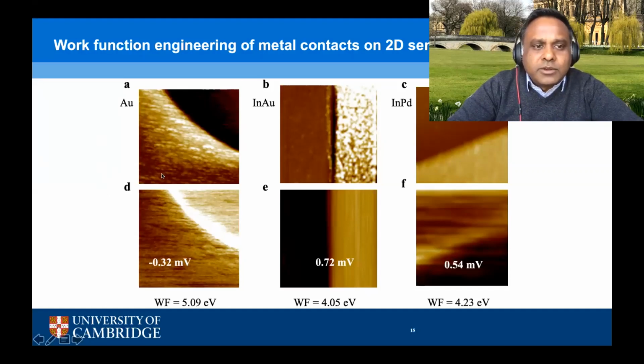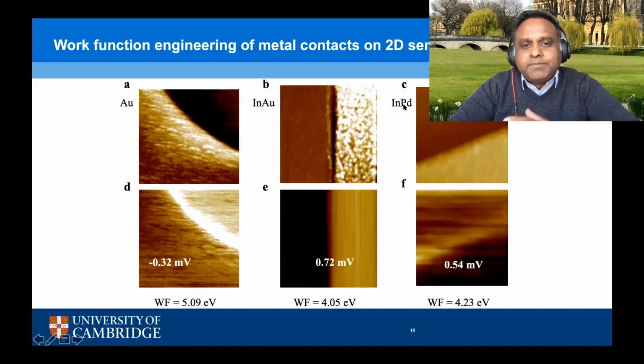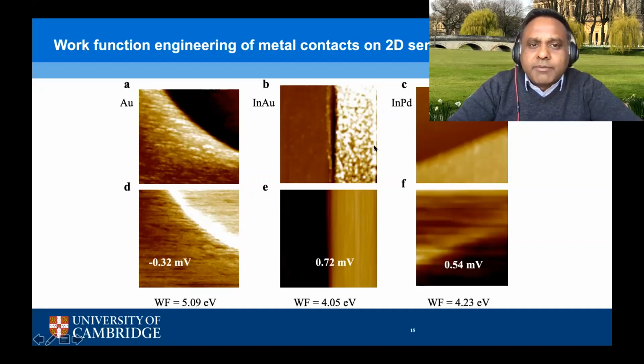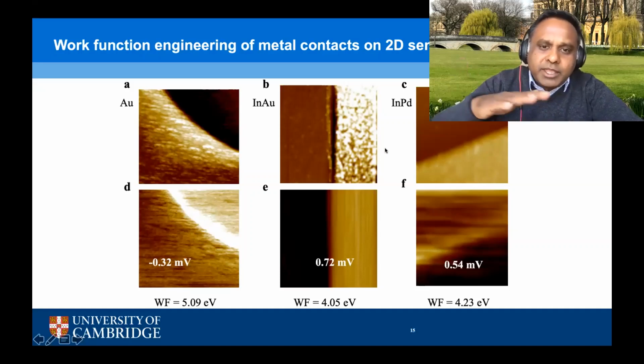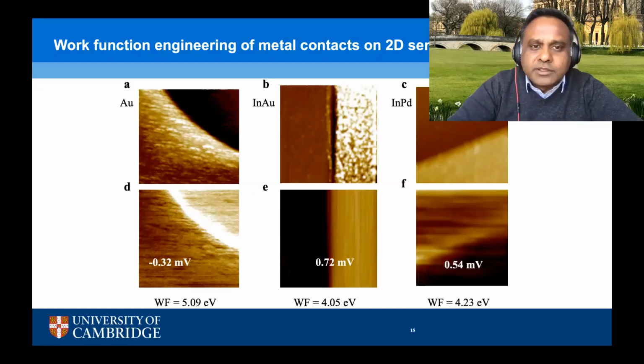And so we've been working on tuning the work function of the electrodes, indium alloy specifically, by alloying it with high work function metals. One thing that I didn't mention in the earlier slides is that the way we make indium electrodes is that we deposit indium first. The typical thickness of indium is of the order of 3 nanometers, and then we typically cap it with gold.